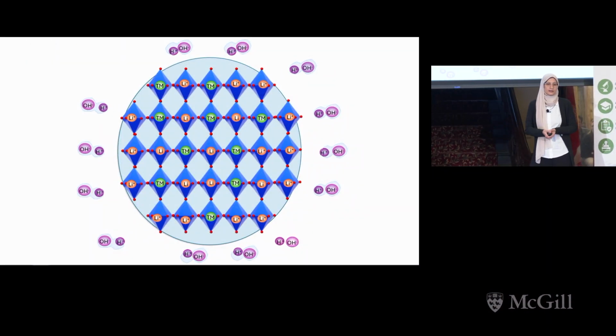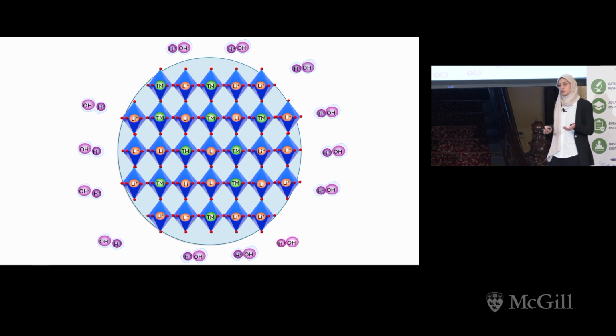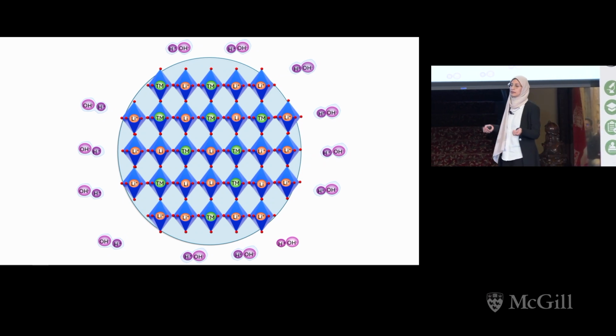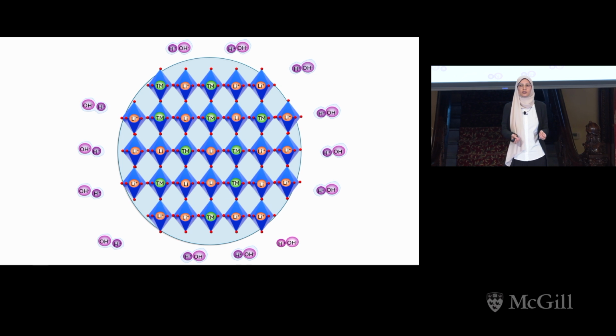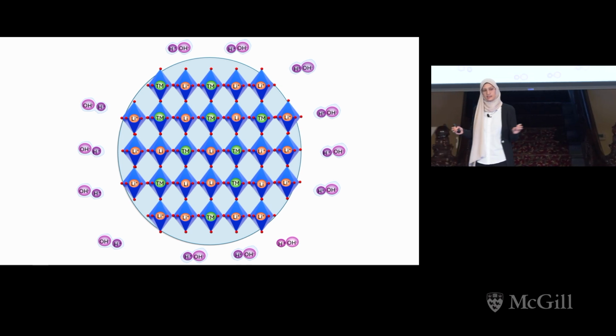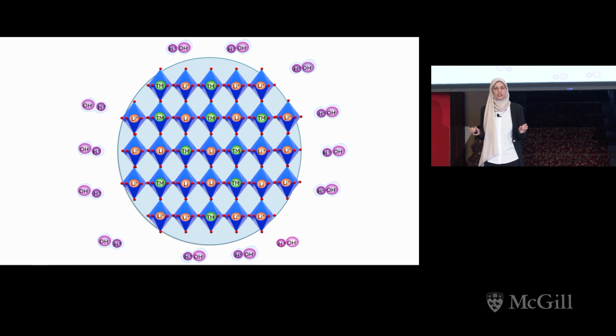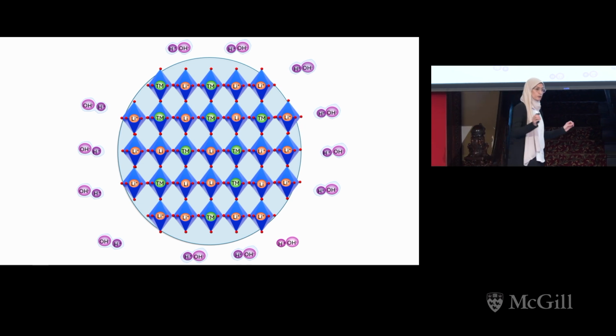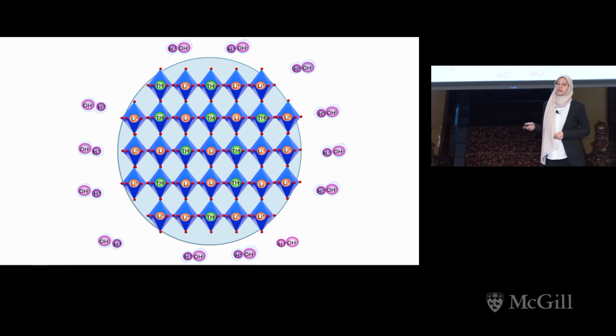And this is what happened. When we tested the performance, or tested the material, we found that indeed we got our lithium back. So now we have our marshmallow particles with our lithium back in the structure. The material is ready to go. Now let me show you the performance of the material.